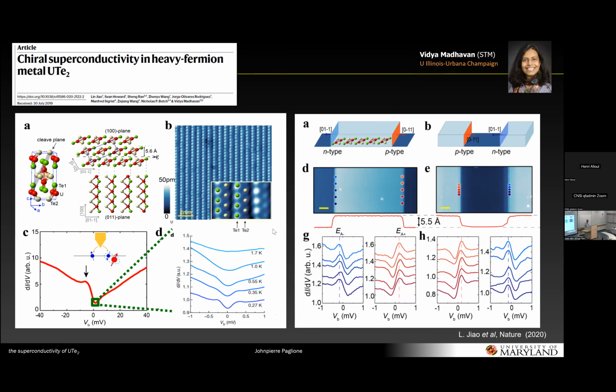So, to add to the confusion, this is one of the earlier experiments, with very nice data on STM, that shows some kind of chiral states when they look at step edges. I could give a whole talk on STM, and I won't. There's a very weak gap on the surface, and when you look at the step edges, there's a chiral kind of response in the bias in the dI/dV that switches when you look at an up edge versus a down edge. And this is only in the superconducting state, and so it was claimed as evidence for some kind of chiral surface states. Again, consistent with a multi-component order parameter.